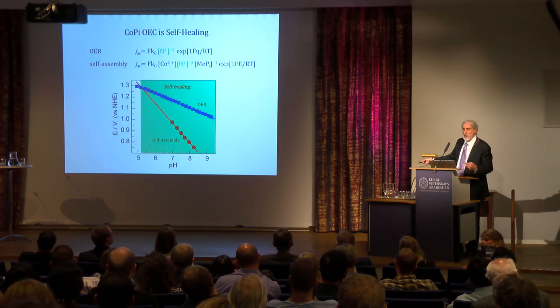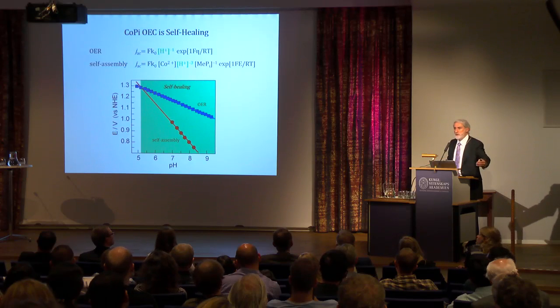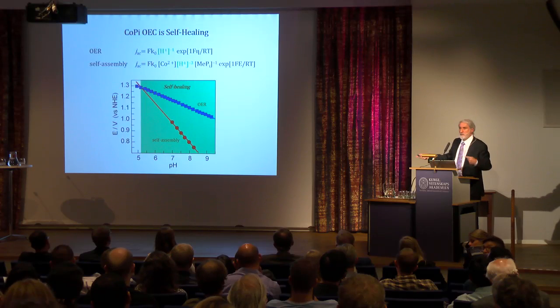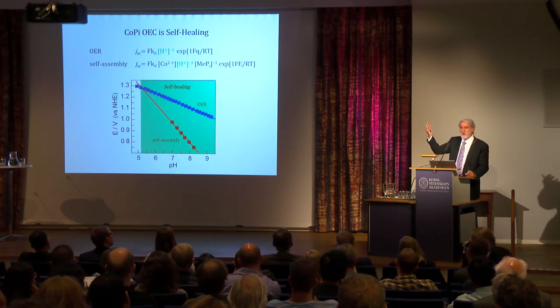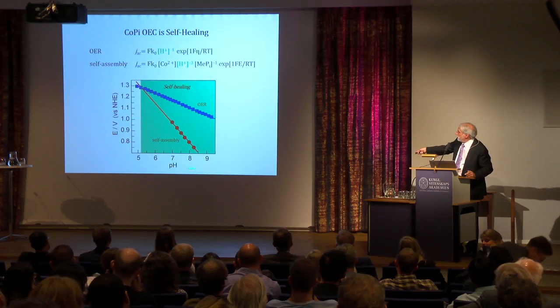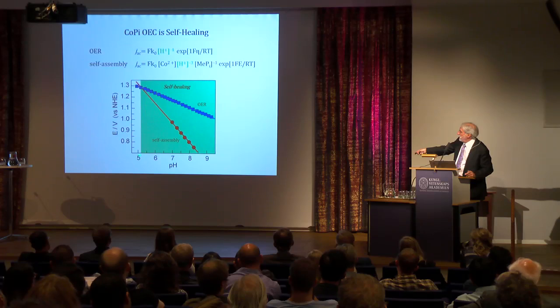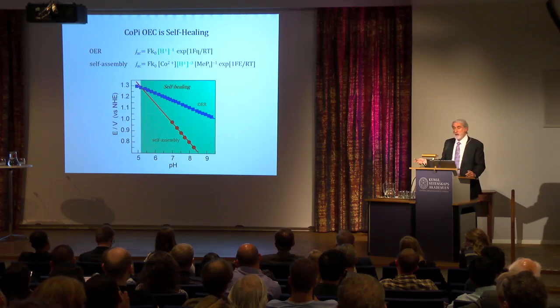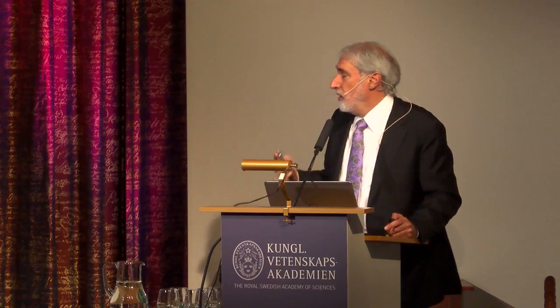If any of the compound decomposes, it can get oxidized back to cobalt-3 and re-self-assemble. So in this entire green area, and this is pH, from 5, acidic, to slightly basic, but around neutral water, this catalyst self-assembles. Now, why is that important? Remember what our goal is. We want to go to the poor.